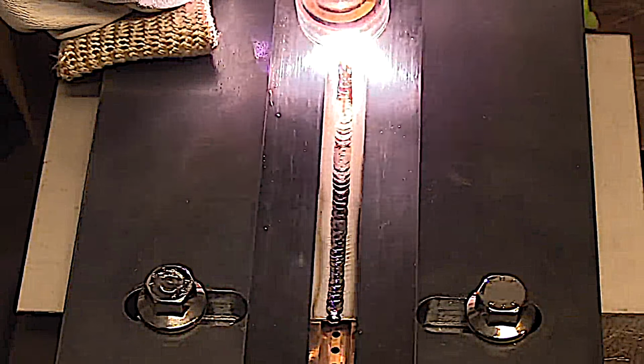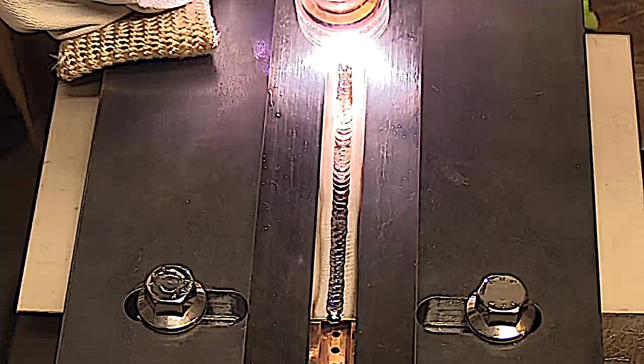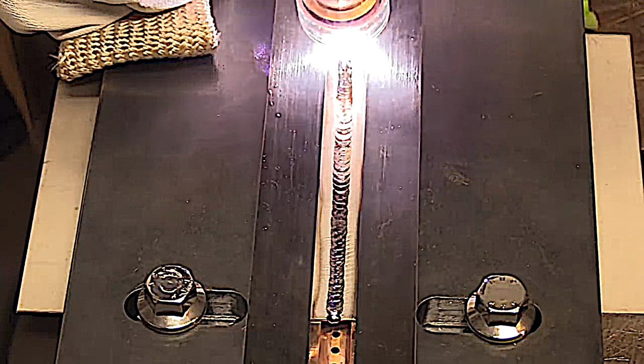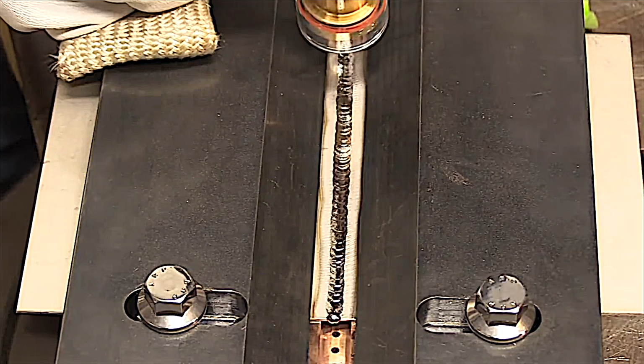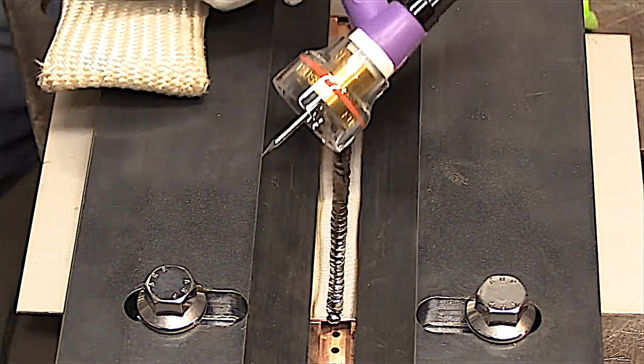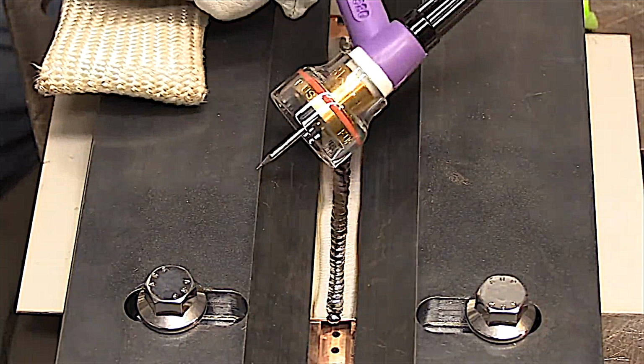I would say the two main things that'll fail you on a test like this on titanium are if you don't get full penetration, because it can be deceiving. You don't want to add too much filler metal, or that can prevent you from getting full penetration. The other thing is porosity, and that is mainly caused by not properly cleaning your metal. You have to file that sheared edge.